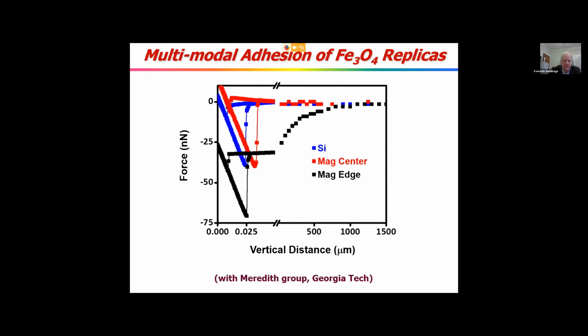Actually, two length scales. On the left is the nanoscale, on the right is the more micro scale. If we put the magnetic pollen particle on silicon, which is not magnetic, you do get van der Waals type adhesion that pulls off the sample at the low range. If you put the magnetic particle in the center of the permanent magnet disk, where there isn't much of a strong field, again, you get the short range order only.